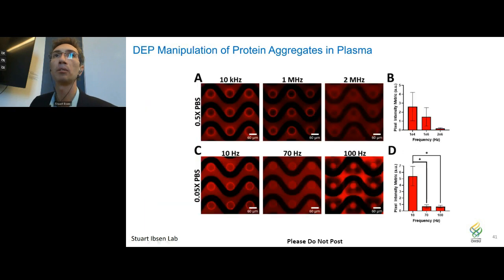And then finally, we're able to also show that we can manipulate where a lot of these particles actually go on the chip. So we can see here that we've got protein aggregates in plasma that are collected in positive DEP here. And we can also push them in between the electrodes in negative DEP if we change the conditions to the correct ones, showing that we're able to manipulate where in the chip we can move these particles, which can really help us not only with these particles as biomarkers themselves, but also in the collection of other kinds of biomarkers too.